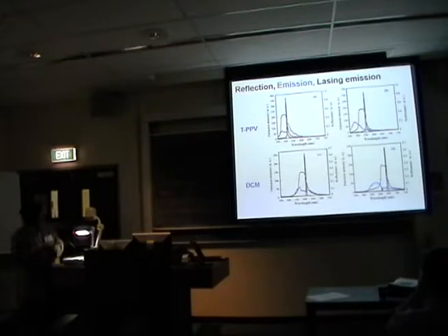Interesting thing, in these two cases, we slightly change the photonic band gap, so that the lower energy edge of the photonic band gap is located almost at the maximum of the emission. And then the lasing occurs here. And this is also the same.